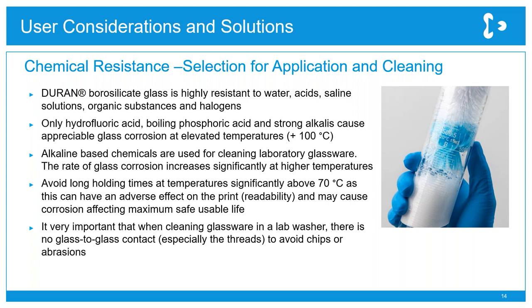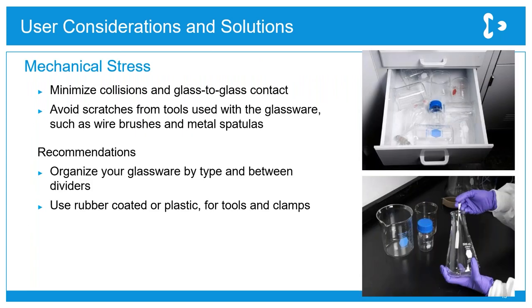It's also a good idea with glass washers to prevent glass-to-glass contact, as this can damage the glassware. Avoiding glass-to-glass contact is also a really good idea when storing the glassware too, and it's best to place the glass products on shelves or in cupboards, but not touching each other. When storing glassware, remember to keep it away from the shelf edges in case it's knocked over and falls down.